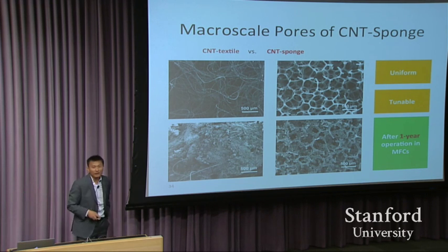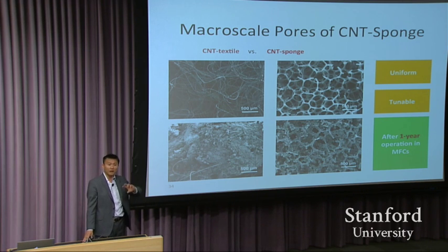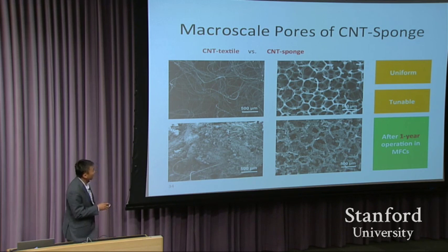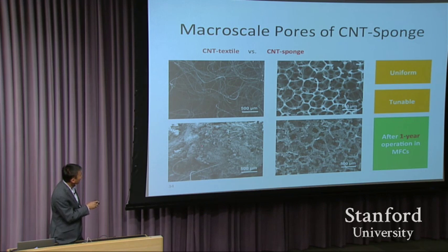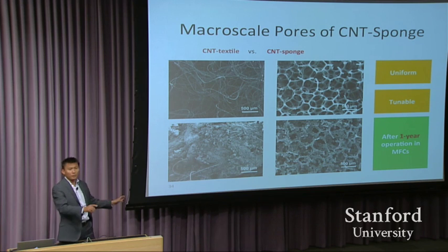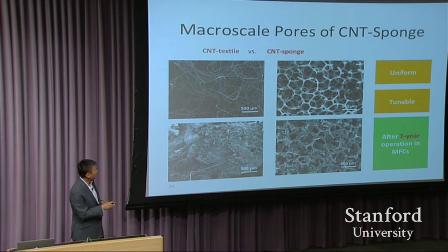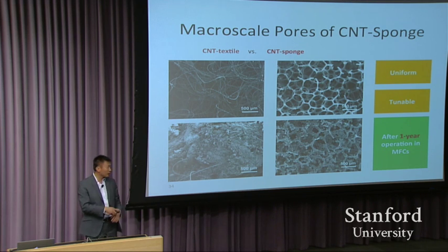This is our initial textile carbon nanotube electrode. After we use this for 1 year, so this experiment, if you do this experiment, a graduate student can only do this for five times, right? And in 5 years they graduate. So this is after 1 year. You see, this is microbes. They already kind of grow into a film. You don't see this porous structure anymore. And this sponge has more uniform pores, right? Big pores right there. And you can still see this hollow space.